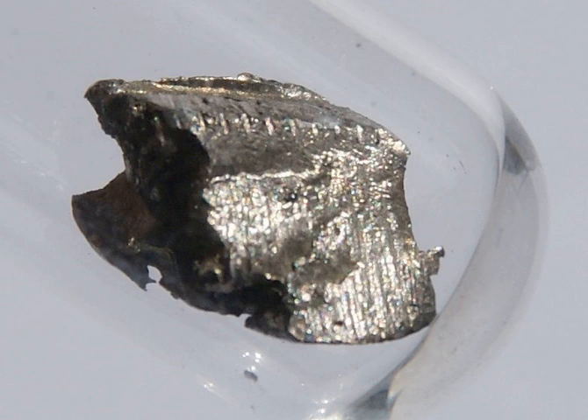Cerium(IV) aqueous solutions may be prepared by reacting cerium(III) solutions with the strong oxidizing agents peroxodisulfate or bismuthate. The value of E°(Ce4+/Ce3+) varies widely depending on conditions due to the relative ease of complexation and hydrolysis with various anions, though +1.72 V is a usually representative value, that for E°(Ce3+/Ce) is −2.34 V. Cerium is the only lanthanide which has important aqueous and coordination chemistry in the +4 oxidation state. Due to ligand-to-metal charge transfer, aqueous cerium(IV) ions are orange-yellow.